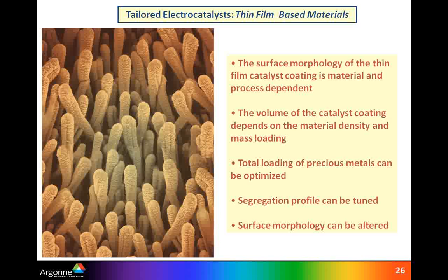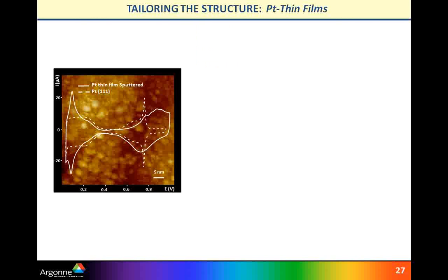So we went to extended surfaces of thin films, and one can see morphology of as deposited pure platinum thin film over glassy carbon substrate. So there was no single crystal as a support or single crystallinity in the beginning, and voltammetry actually resembles voltammetry of what is supposed to be polycrystalline platinum, which is given here as a solid white curve.